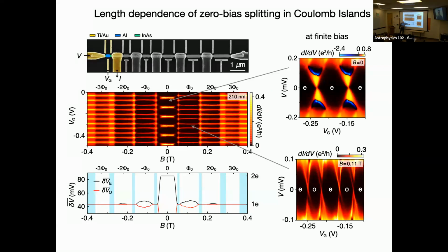But this splitting of the spacing, showing that the odds are smaller than the evens every time, is something worth studying. Why? Because if I take two Majoranas at the end and I bring them together toward the ends of the wires, the energies that made those states degenerate when they were far apart will not be degenerate anymore. Now those split in energy. Is that what I'm measuring? The split in energy, the finite size gap that's responsible for these even-odd spacings when there's a finite lift of the degenerate state? Let's find out.